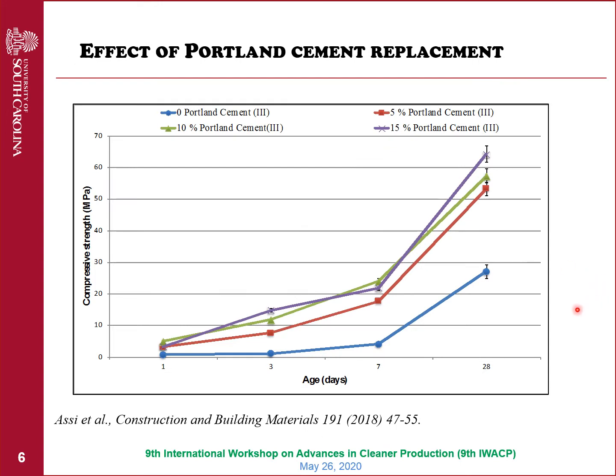So our next step was to eliminate the need for external heat, and we did that by introducing 5 up to 15% of Portland cement. So the need for external heat was removed, and the initial and final setting time was also improved. Also, we reached up to 65 megapascal.